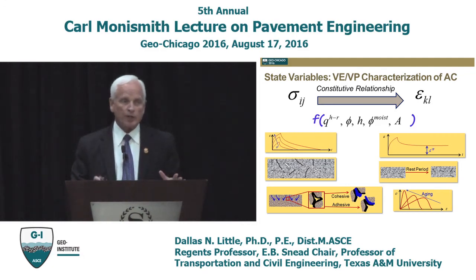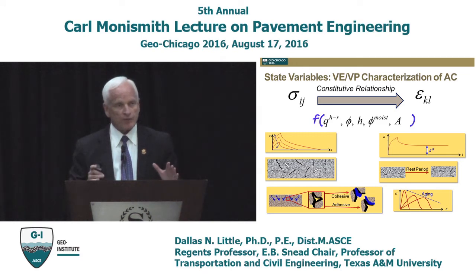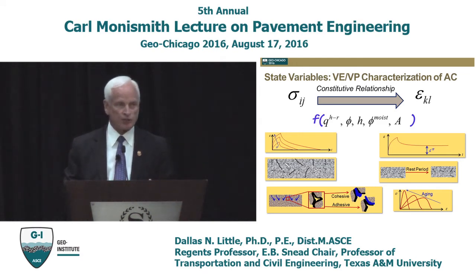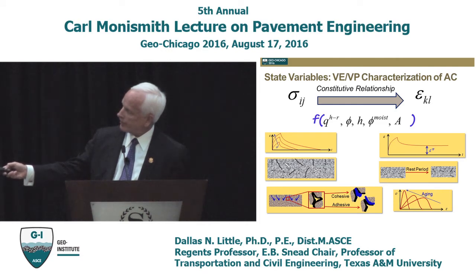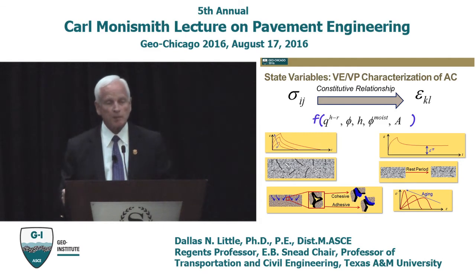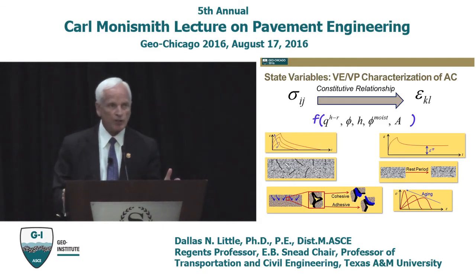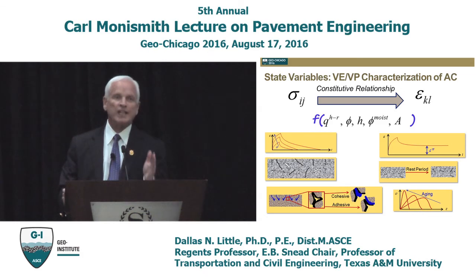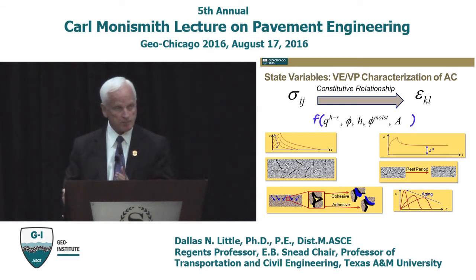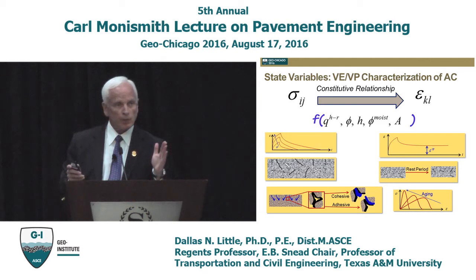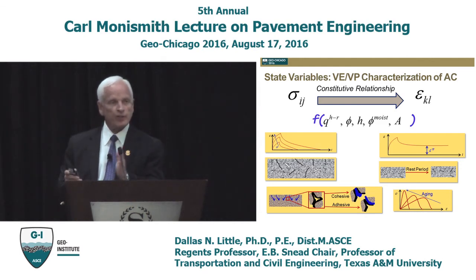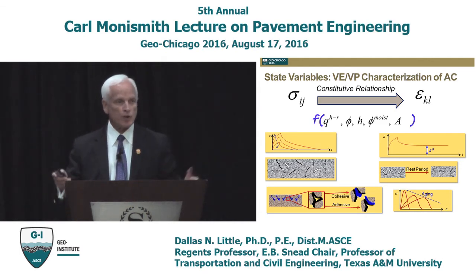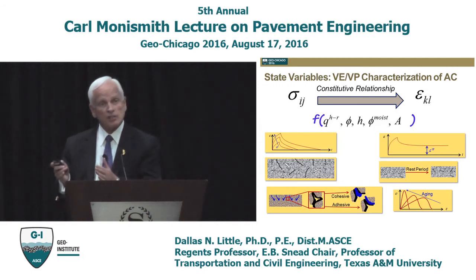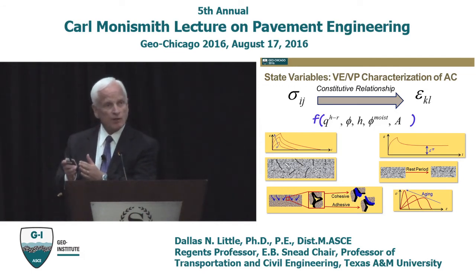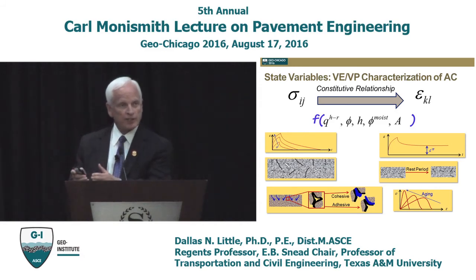Besides doing that, we have a number of state variables that help define the response of the asphalt. And I've listed those state variables here. The first one, the Q term, is simply a definition of how the failure surface changes. It's a dynamic failure surface. So when we calculate damage, we're calculating damage against a moving failure surface that hardens with load applications, and if there's an extended rest period between or among load applications, there's a bit of a relaxation.